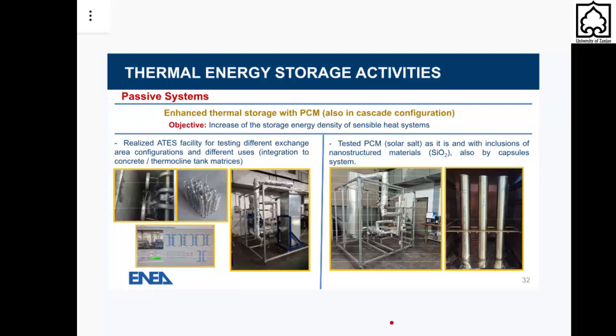And therefore, two strategies have been conceived. On one side, to enhance the exchange surface area between the heat transfer fluid and the phase change material, as visible in the pictures on the left-hand side of the slide. And on the other side, to increase the intrinsic thermal conductivity and diffusivity of phase change materials by the inclusion of nanostructured materials. And so we have worked on different materials, mainly mixtures of binary molten salts as such, and with the inclusion of silica, metals, carbon nanotubes, also to increase the energy storage density and the temperature stability in the discharging phase.